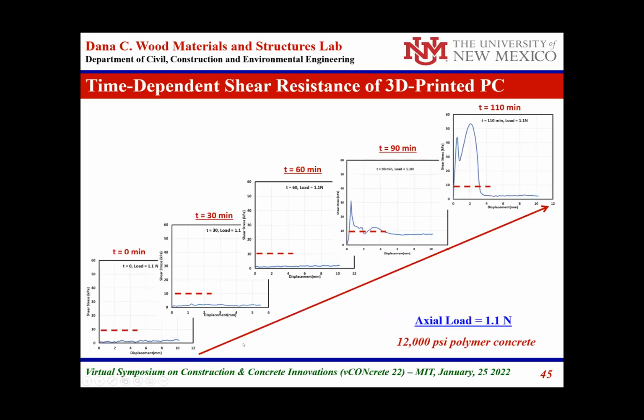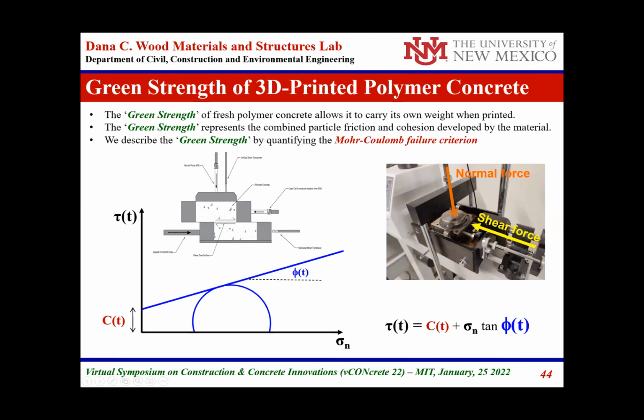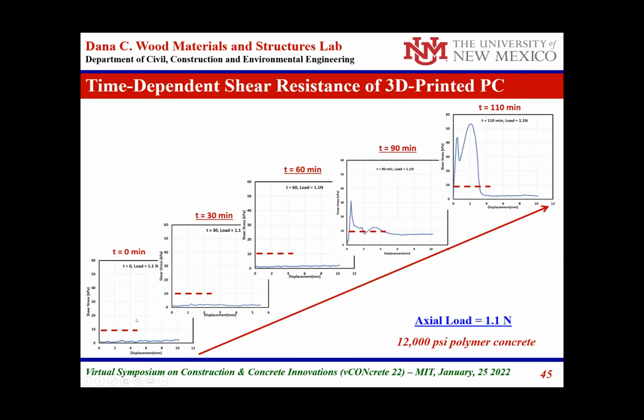To do this, we actually built the polymer concrete and did this test, as you can see on top, where we are applying normal stress and shear stress and measuring the stresses required with time. You can see we are repeating the stress with time from time zero of the same polymer concrete mix. Every one of them is a different sample, of course.